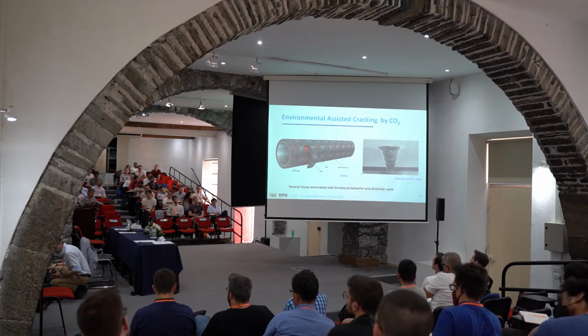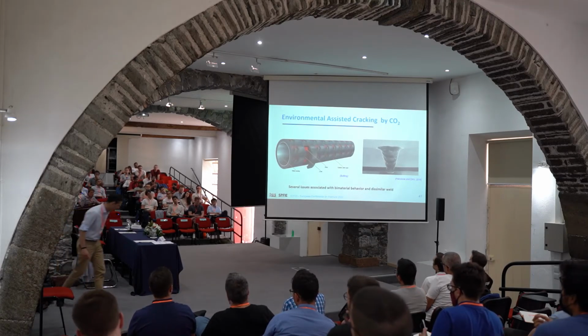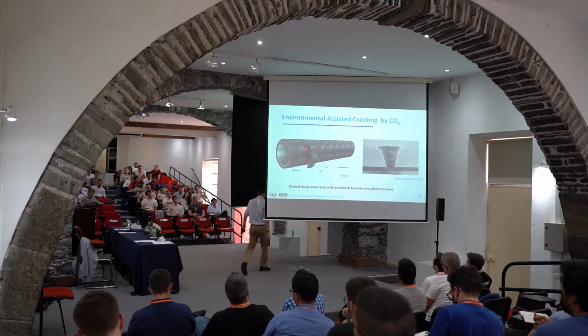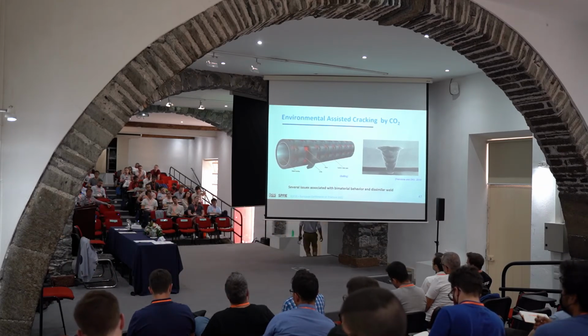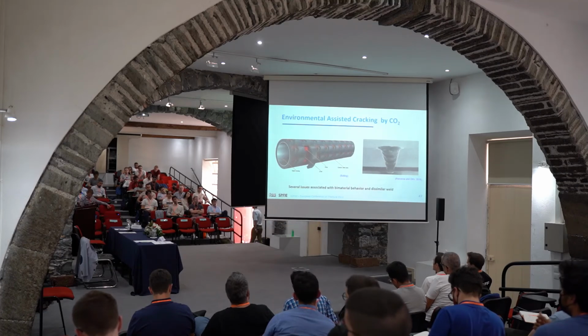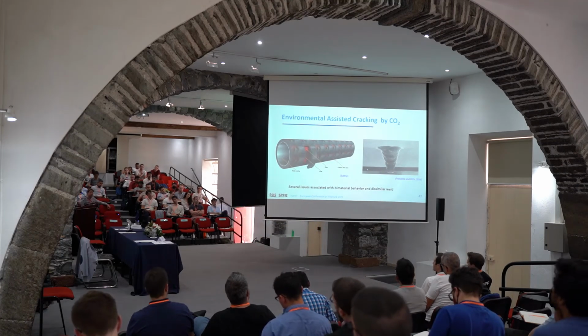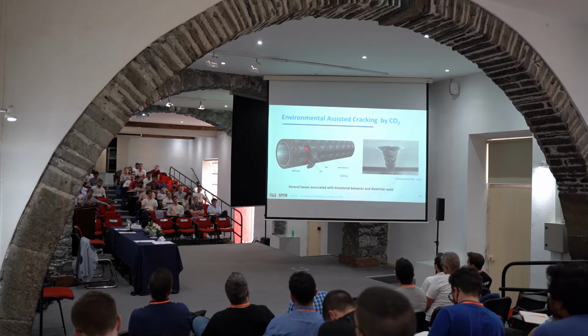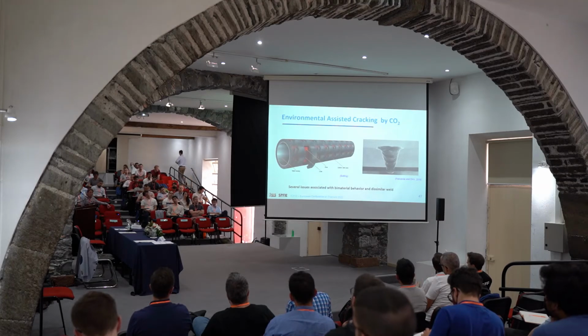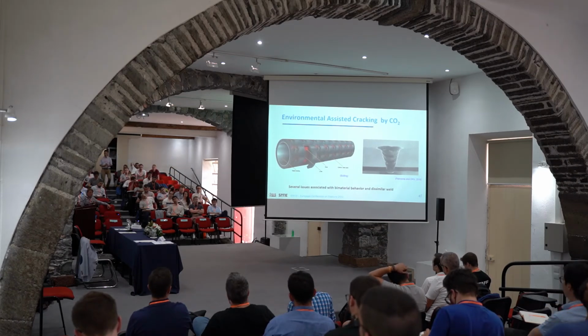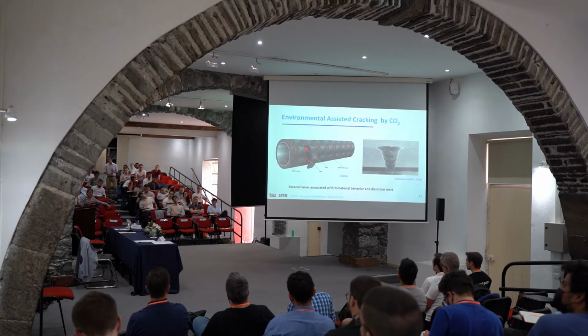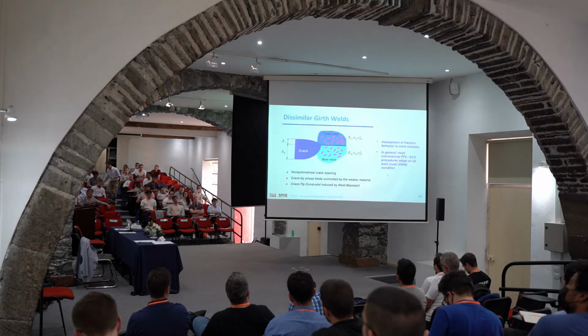But the problem here is the welding. I told you, welding is the weakest link in any structural component. Because this is an Inconel layer, the welding is also Inconel. So believe it or not, it's a very expensive procedure. They make a truly dissimilar weld. It's truly dissimilar. So it's Inconel inside and the outside is the base metal weld. And there are several issues that we're going to address.